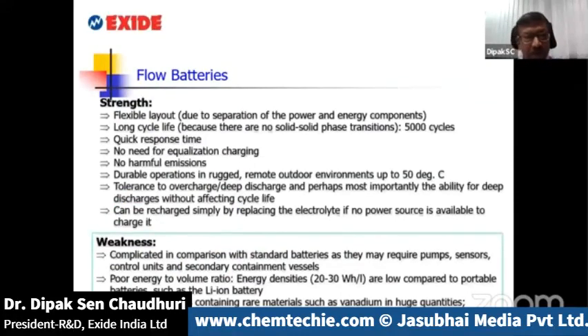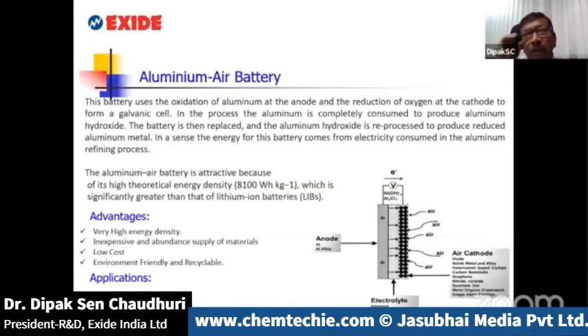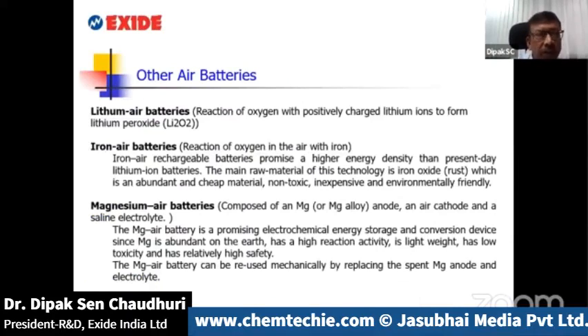However, this has certain weaknesses. It is complicated in comparison with standard batteries, because it requires pumps and sensors, so maintenance becomes an issue. It also has a poor energy to volume ratio. Aluminum air is another technology which is being much discussed, but this is not really a rechargeable battery. It's more a primary battery, where the aluminum reacts with the oxygen, gets oxidized, and over a period of time gets completely chemically converted. And at that time, the electrode has to be replaced with a fresh aluminum electrode, and this cycle can go on. However, the main advantage of this is its extremely high energy density because of the very low weight of aluminum. There are many other metal air batteries, all of which basically function on the principle of the redox reaction taking place inside. So you will keep hearing every now and then the success of magnesium air, silicon air, and other applications.